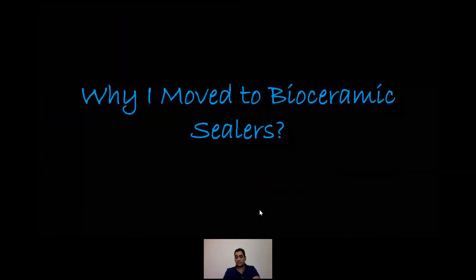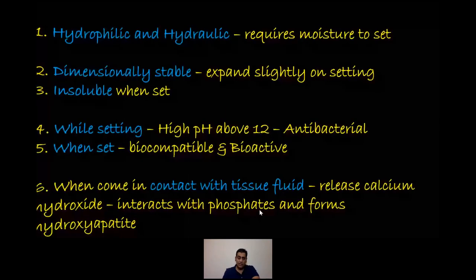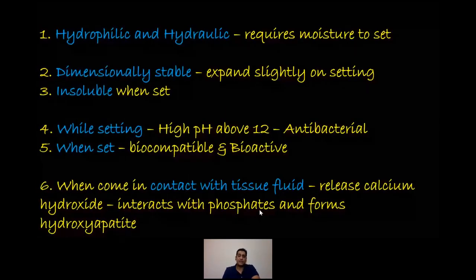Summarizing the benefits of bioceramic sealers: it's hydrophilic and hydraulic, requiring moisture to set. It's dimensionally stable, expanding slightly on setting by 0.2%, and once set it's insoluble. While setting it has a very high pH above 12, making it antibacterial. When set it's biocompatible and bioactive. When in contact with tissue fluids it releases calcium hydroxide, which interacts with phosphates to form hydroxyapatite.